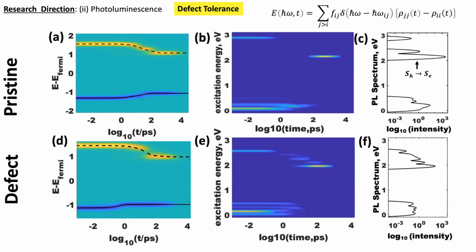At time zero, photoexcitation promotes an electron from valence to conduction band. As time passes by, the electron loses its energy into lattice vibration, and the hole also loses its energy. Then at some time they recombine, and therefore these yellow, orange, and blue stripes are decaying and disappearing. The time when they disappear corresponds to the recombination time.